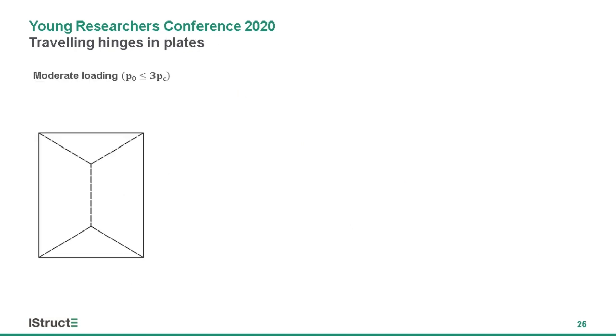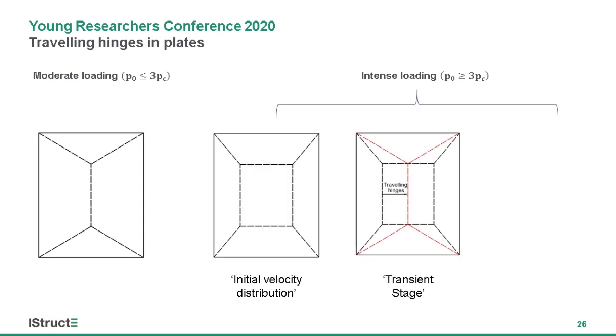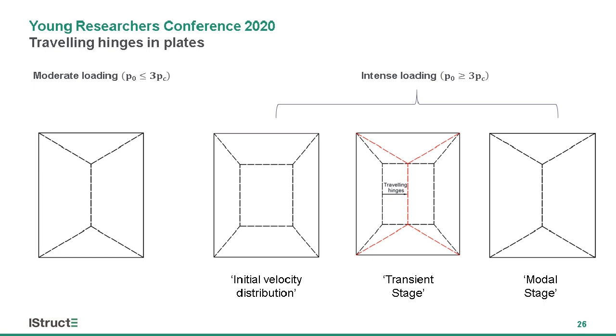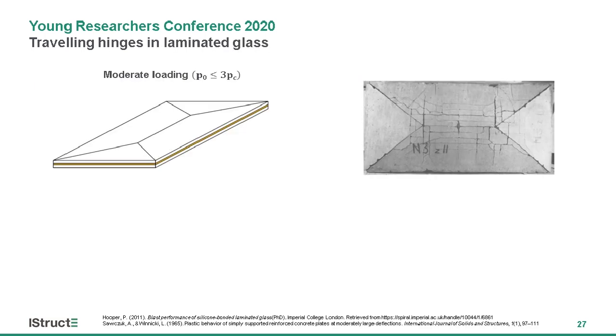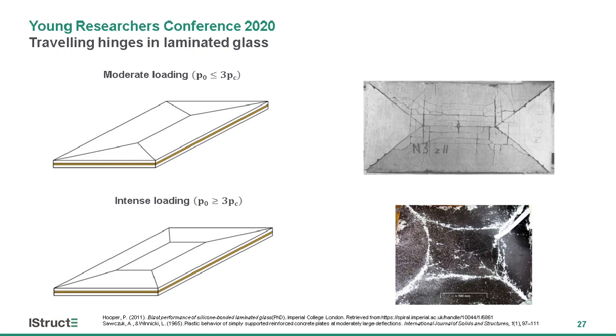The same principles can also be extended to two-way spanning plates such as laminated glass panels. Again, the collapse mechanism under static loading or moderate dynamic loading is different compared to the propagating yield lines observed under intense loading. Inertia effects are therefore considered to be responsible for the failure pattern of laminated glass panels repeatedly observed in blast tests.